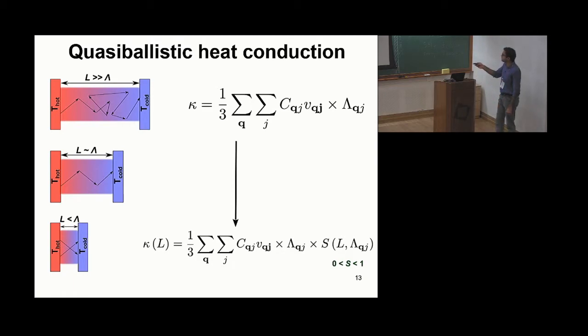In the diffusion regime, you get this precise expression for thermal conductivity. When you go to the quasi-ballistic regime, you get a different expression where thermal conductivity is no longer a constant, but depends on L. And the L dependence comes from this function called the suppression function.